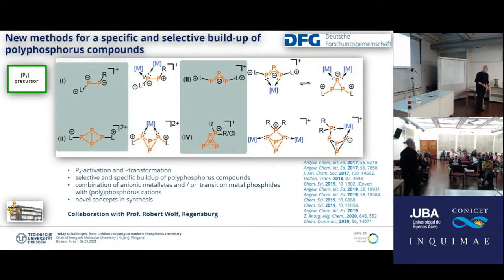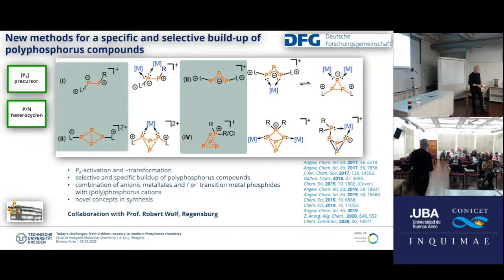So what we're trying to do over the years is make new kinds of precursors, motivation you will see in a moment, new kinds of PN heterocycles, because they are quite interesting. If you have 2D materials and you replace nitrogen by phosphorus, for example, you change the electronic properties. And very interesting photoluminescent materials derived out of this. So we're starting also to make new kinds of LEDs, which contain phosphorus. Don't get mistaken by a phosphor, that's just something else, but really the element phosphorus in those materials, and they make quite promising new applications. So we just recently published, for example, a phosphor which has room temperature phosphorescence, which is quite something. And so this is where it is beneficial to develop new synthesis, being able to make compounds which have phosphorus instead of nitrogen, which is not that simple, to be honest.